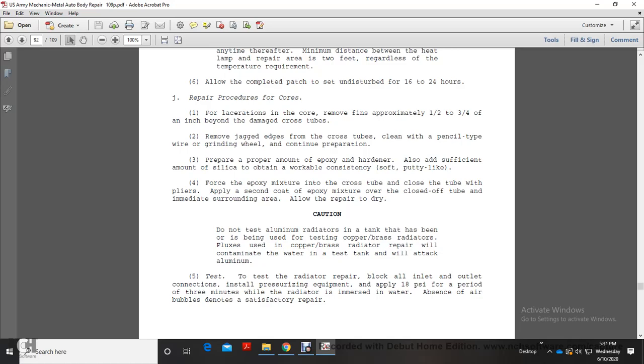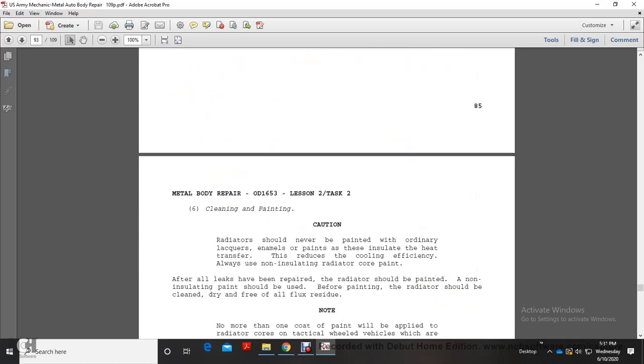Caution: do not test the aluminum radiator in a tank that has been used to test copper brass radiators. Flux from copper brass radiator repair will contaminate the water, and the test tank will attack the aluminum. Test: to test the radiator repair, block all inlet and outlet connections, install pressure equipment, and apply 18 psi for a period of 3 minutes while the radiator is immersed in water. Absence of air bubbles denotes a satisfactory repair.